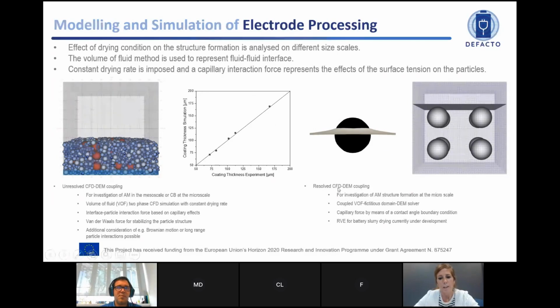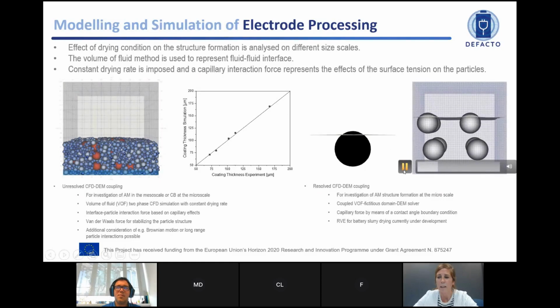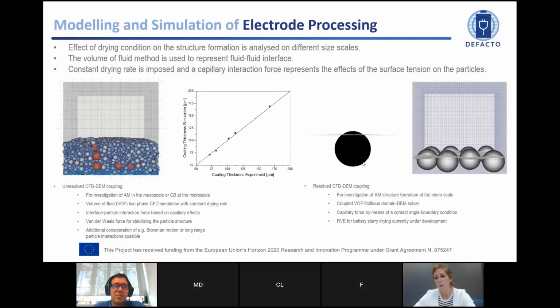For the resolved CFD-DEM coupling, basically we aim to investigate how the active material structure is formed at the microscale, and you can see some examples here of the single particle displacement, and then another sample of 8 particles in a cubic configuration displacement through the drying steps. So having this information in mind, later we can proceed with the optimization and validation.